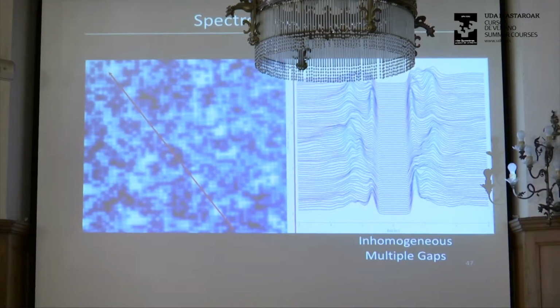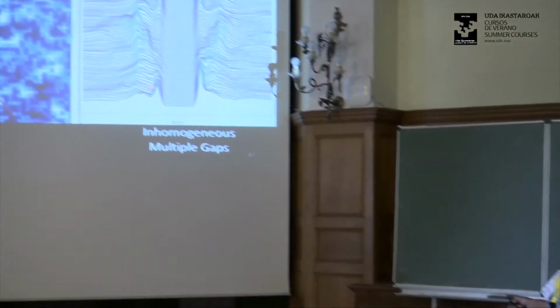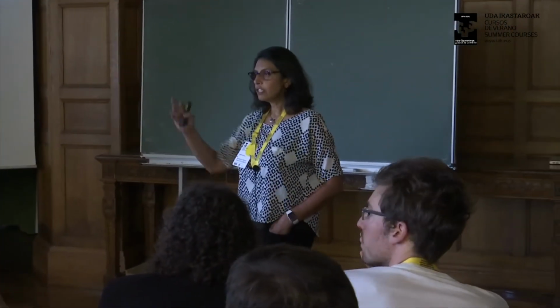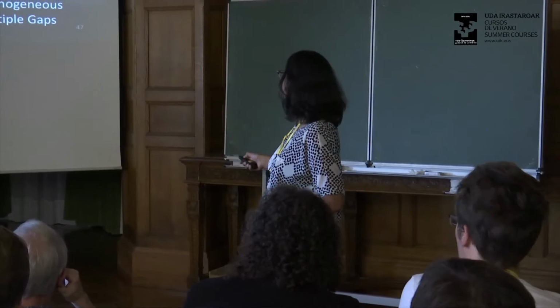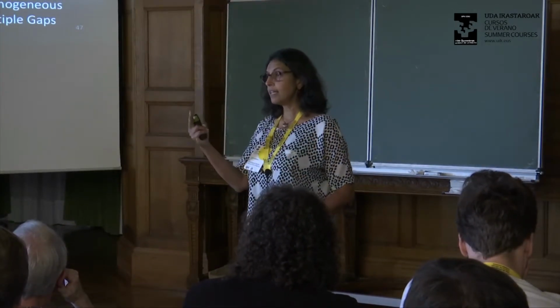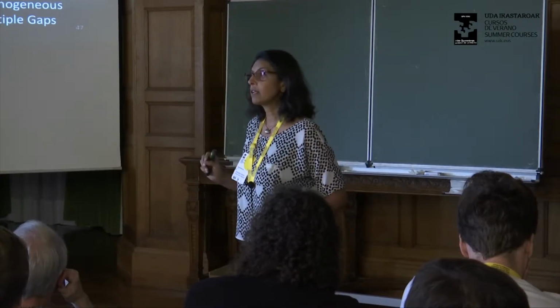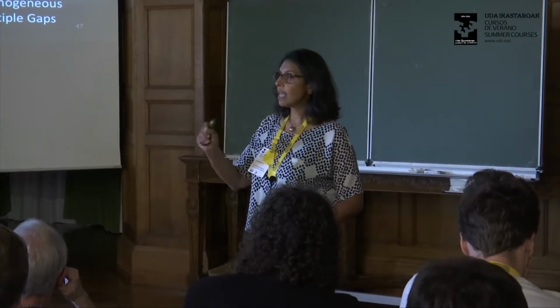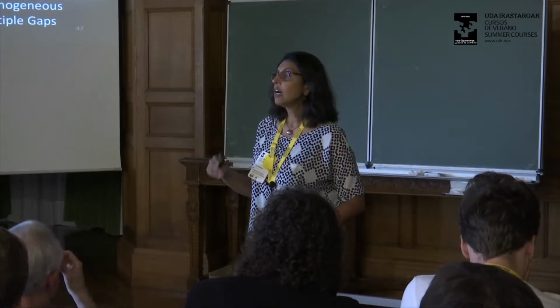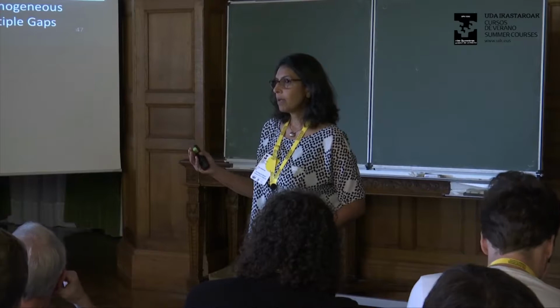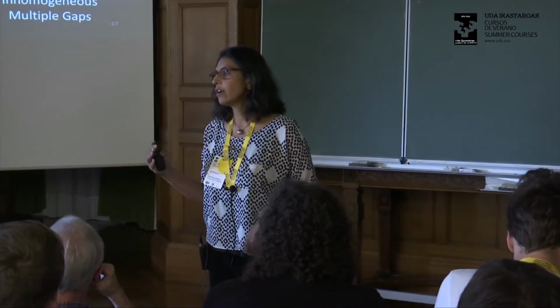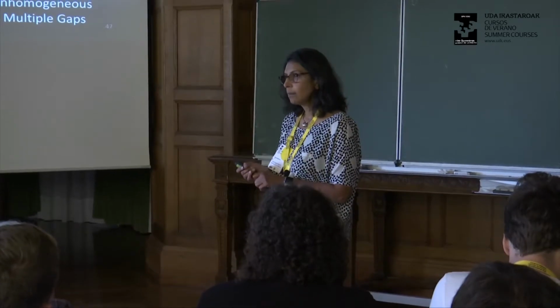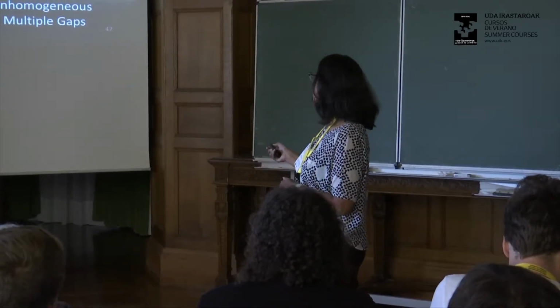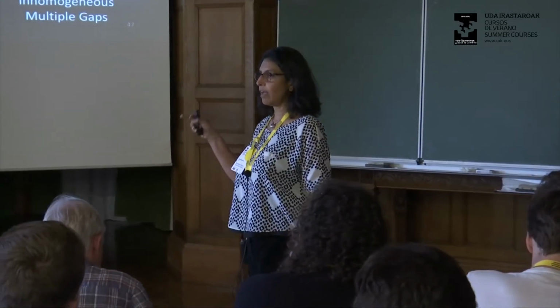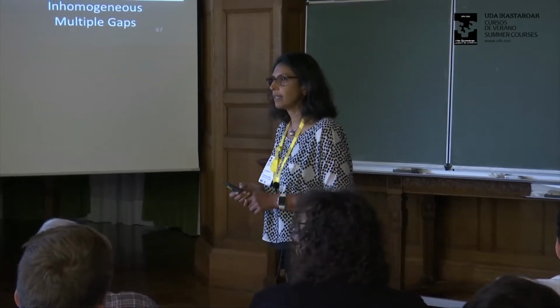What we would do, yes? What do you actually call a gap? Ah, that's a really good question. For us, anything that has a coherence peak is a gap. There are 2 criteria. One is that there should be something that looks like a peak. And the second, which is really, really important, is that it should be particle-hole symmetric. So if you see the same feature on both sides of the Fermi energy, then you can define it as a gap. Now, there are certain circumstances where phonons also look particle-hole symmetric, but in this case, you'll see from the data that everything that we pick up is actually a superconducting gap.